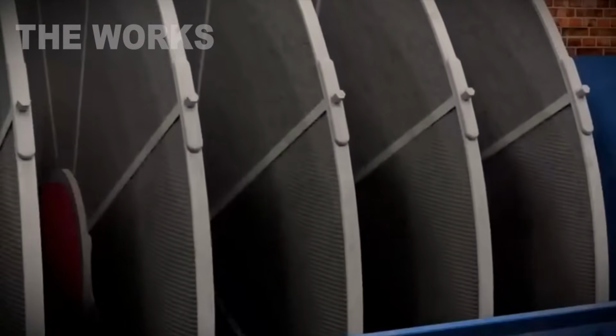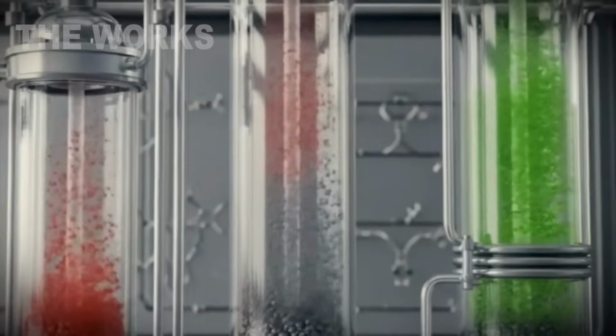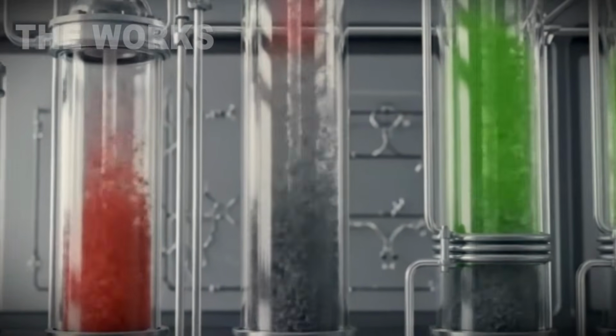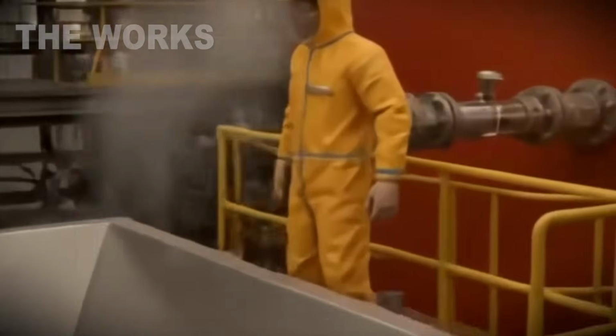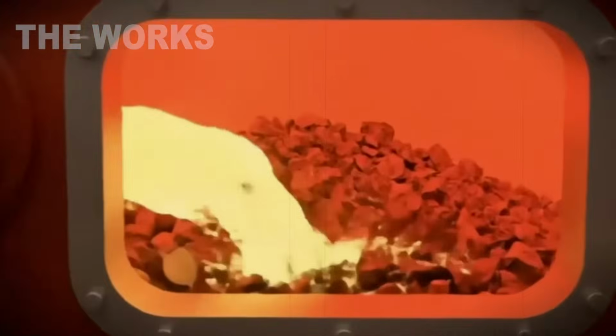Pour the slurry into the flotation machine. Tank volume, 13,000 gallons. Air pumps in from below. Pressure, 30 pounds per square inch. Flow rate, 10,000 cubic feet per hour. Air forms billions of bubbles 0.2 inches across. Bubbles stick to iron particles. Lift them up. Foam forms on the surface.